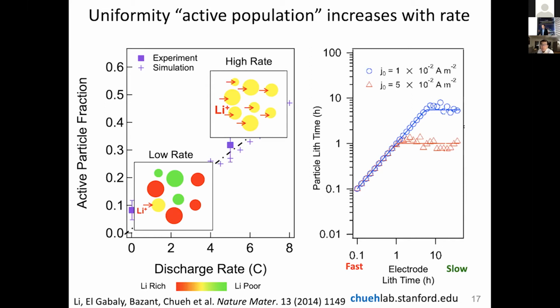And the plateau region is very interesting because that means you are slowing down the electrode intercalation, but you're not slowing down the particle intercalation. And this is the regime where the active population drops and you're using less and less of the particle. So this phenomenon, which we discovered in the early 2010s, was very uncomfortable because this went against most kinetic understandings of intercalation. So we dug a little bit deeper, and let me show you just a cartoon of what we found.